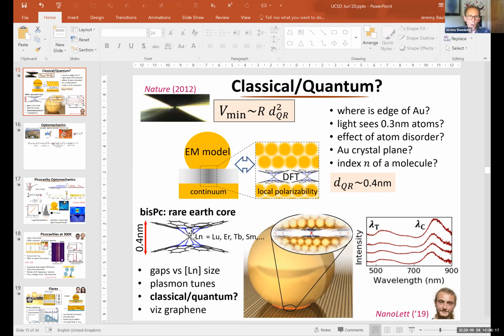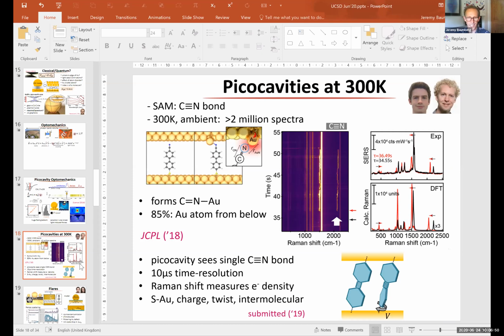So there's no way that we can really use classical theory to predict this. And indeed, when we look at the modes that we see, they're not predicted by classical theory or the quantum theory. So it's really not clear what's going on. And that's a bit of a similar question to what happens when I put a TMD in the gap here. So it's really not understood how you bridge the classical and the quantum domains here. So the quantum domains of your emitter or your DFT in the middle here, and classically you need to treat a much larger region of gold atoms. So this is, I think, a huge challenge in the field at the moment, which is really interesting.